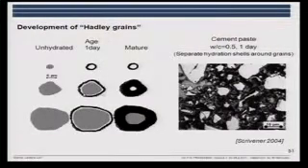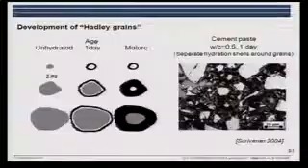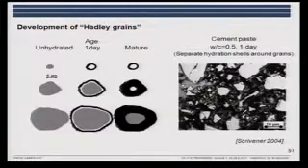Here we can see that we have a rim on the two others. When the samples are mature, we still have this closed pore where the small grain was, some in the middle size grain, but none in the large size grain. And here you then see porosity where you have some rims here. In this backscattered image, all that is dark is the porosity.